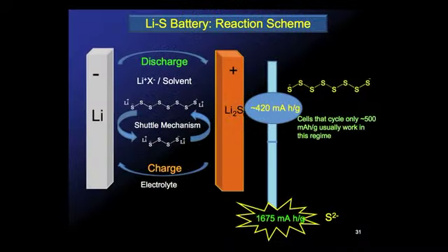We've gone a long way in looking at different sorts of carbons, which has led us into interesting avenues. So I'll briefly describe these for the sulfur cell. I already explained that you start off with elemental sulfur in this cell. So this is just described by this block of sulfur. And if we then start reducing, we go through our cascade of polysulfides, including S8 2- and the S4 2- species. And in principle, these are then contained within this carbon host, which is not shown in the diagram.